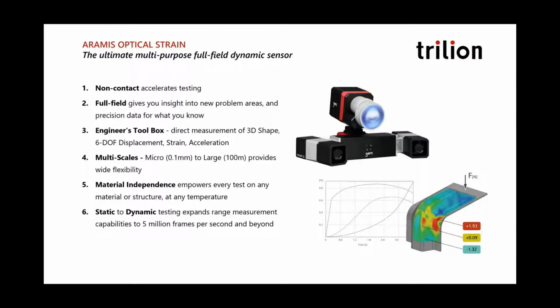With our equipment, we can just use a broad range of different cameras. Most cameras can do quasi-static to low dynamic without any issue. But we also have cameras that can go up to 5 million frames per second, which we use for glass fracture and these kinds of things, but are just a complete range of capability of high speed. And we'll be talking tomorrow about high speed work.